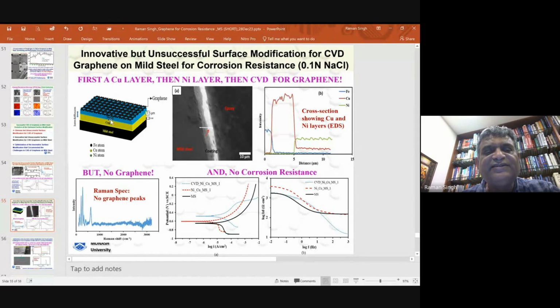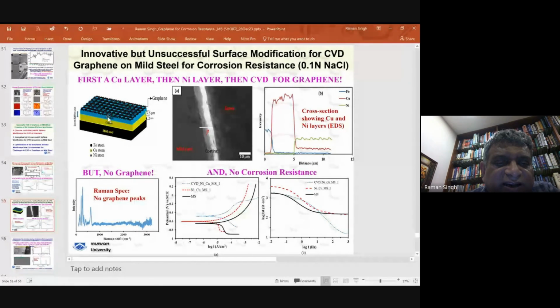You remember I said that copper has very poor or very low, insignificant solubility of carbon. Why don't we put a layer of copper in between nickel and mild steel, so that carbon that is solubilizing in the nickel in the early part of CVD will not get to mild steel. It will not leak into mild steel. Copper will stop because copper does not have solubility of carbon.